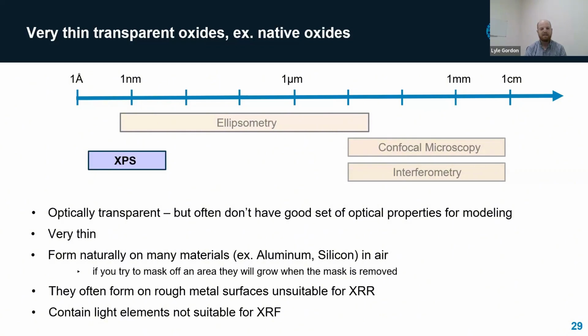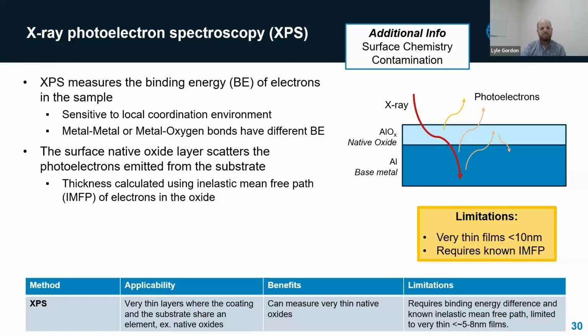And in other cases, like if you're familiar with many metal surfaces, they're not polished like wafers, so we're not able to use X-ray reflectivity here. And for these oxides, they contain light elements, which aren't suitable for X-ray fluorescence, which is typically best on heavier elements that produce more X-rays. So we'll show you here a nice application using X-ray photoelectron spectroscopy to measure these layers. So a really quick intro. This probably won't teach you everything, but hopefully enough to understand the application.